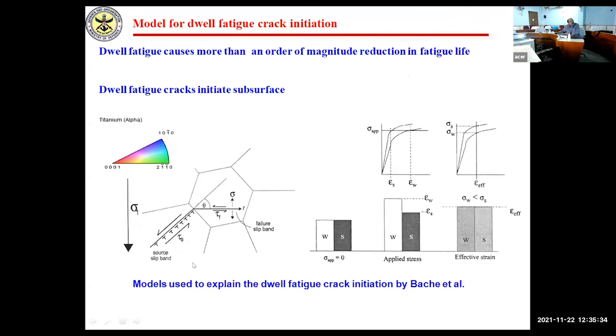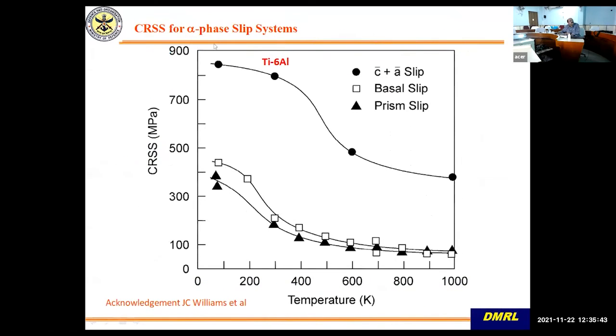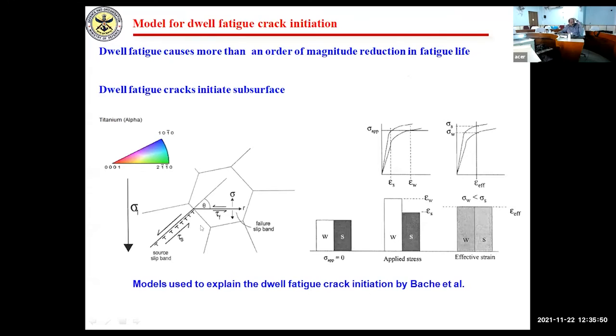So this region is oriented for easy deformation, whereas there is a neighboring region which is oriented for difficult deformation. That is, C plus A slip has to be activated. Other slip, critical resolved shear stress does not occur. So what happens is this deforms and unloads onto the hard oriented, not hardness wise, but deformation wise. And this stress adds on to the applied stress, and it causes fracture or cracking. That is how the dwell fatigue crack initiates. That is, the adjacent oriented easy slip region deforms and unloads onto this hard oriented region, and cracks form.